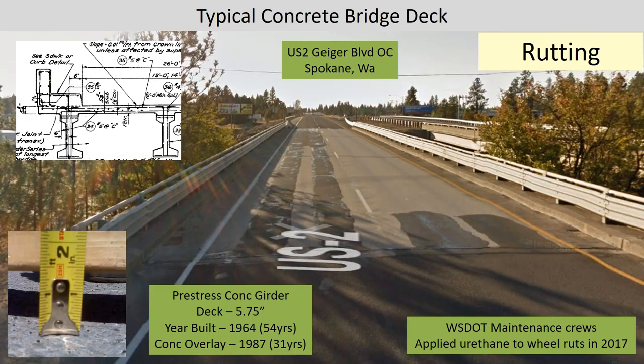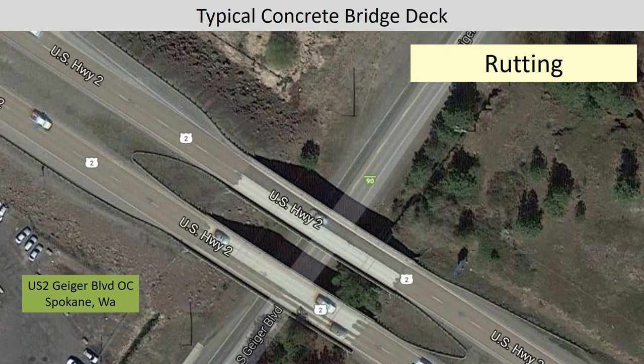Anthony showed a picture of this bridge. If you're familiar with the Spokane area, it's the route to get to Spokane Airport on Highway 2. You can see that the bridge was built in '64. About 23 years later, we put a concrete overlay on it. And then nearly 30 years later, we have close to an inch to an inch and a half of rutting. So maintenance went out and tried some different techniques, partially filling some ruts, doing some rut fills, and then doing material over the whole lane. And these are kind of temporary repairs. You can see an aerial view of the same set of bridges. Realistically, what's going to have to happen is this concrete overlay is going to have to be removed and replaced.